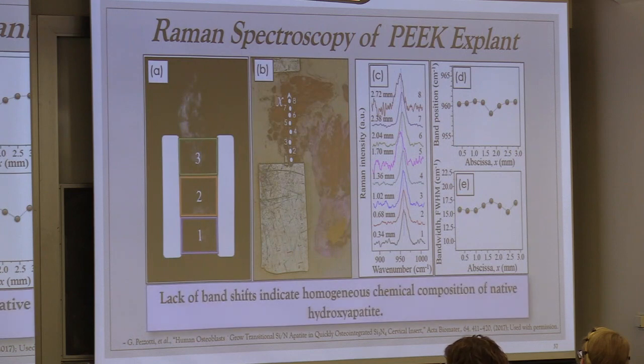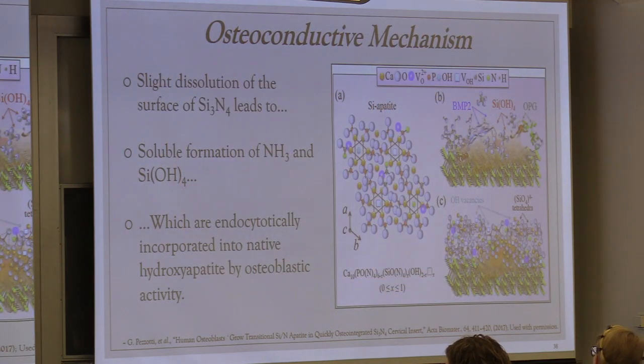So if you look then at the PEEK implant, which we did the same thing there, and first of all, you can see that there is not much in the way of integration of the PEEK implant to the bone. But if you look at the chemical and physical composition of the material, you see that there are actually no changes, which is what you might expect for an inert material. So it really points to the fact that silicon nitride is osteopromotive. So now what happens here is that slight dissolution of the surface of silicon nitride leads to the formation of soluble ammonia and silicic acid, which are then endocytotically incorporated into the hydroxyapatite by action of the osteoblasts. And so a very good osteopromotive characteristic.